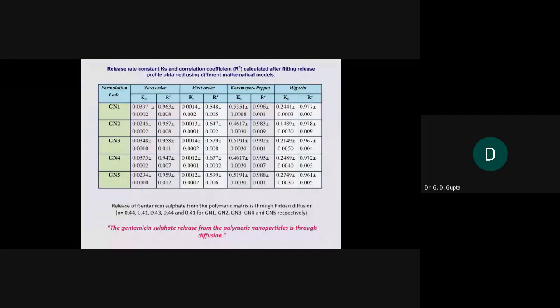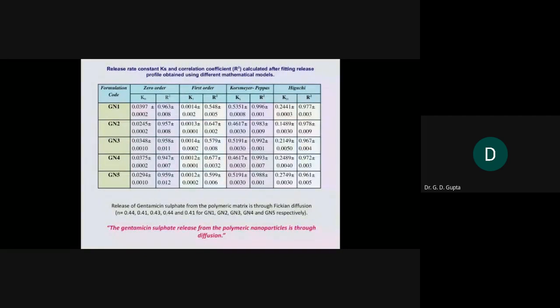So we can say that the values properly fit the Korsmeyer-Peppas model, and the n values were found to be 0.44, 0.41, 0.43, which means that the release of the drug from these polymeric nanoparticles is through Fickian diffusion. That means no erosion is taking place, the polymer nanoparticle remains intact, and the drug is released from the nanoparticle slowly and slowly through Fickian diffusion.